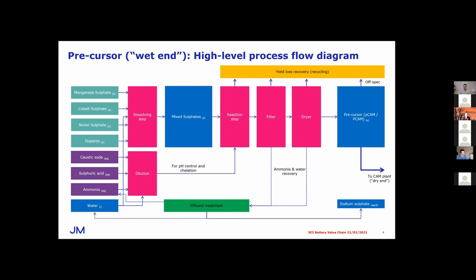And the sodium sulfate can be dried and then bagged and sold, but one of the challenges for this industry, but also for the upstream raw materials, is that sodium sulfate's not a very large market, especially outside of Asia. And it's also a problematic byproduct to dispose of because it forms a gel-like substance if you expose it to moisture or water. So one of the big challenges for the industry, particularly for lithium production, but also for the precursor production, is what to do with the sodium sulfate.